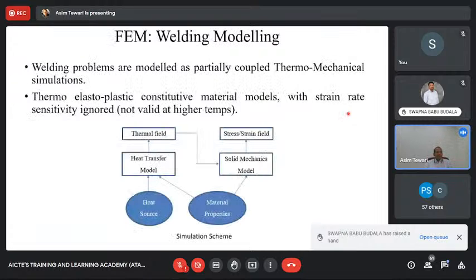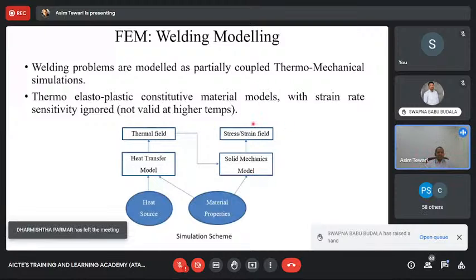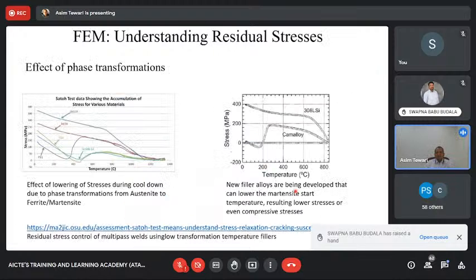So this is what we validated for welding and additive manufacturing, and I'll show you some of the simulations. You have a heat transfer model, which leads to thermal fields, and those thermal fields lead to strains. And those strains, based on constraints at the boundary, if it's a no traction or no displacement boundary, will lead to stress strain fields. So this is the overall aspect of the modeling of the stresses and the thermal aspects.